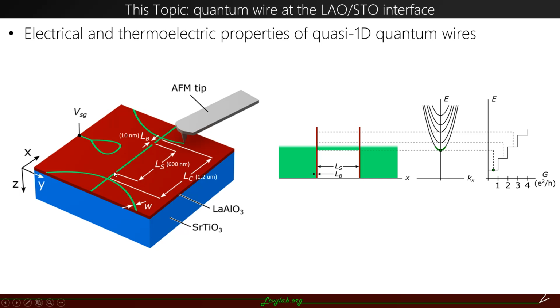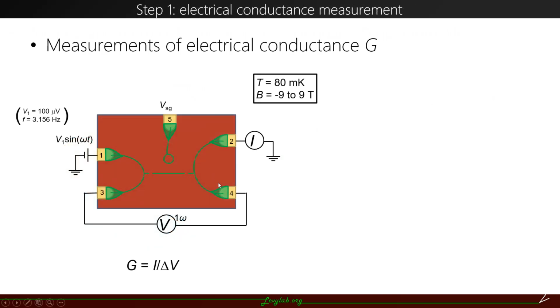So these 2 barriers make it possible for the side gate to tune the chemical potential of this quantum wire, and as a result, we can measure quantized electrical conductance as a function of the side gate voltage. There are also leads on both sides of the main channel to allow us to make the electrical and the thermoelectric measurements. The first step is to measure the 4-terminal electrical conductance.